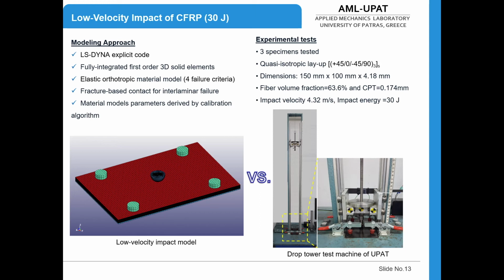And the idea is that we have this impact tower. We use this quasi-isotropic layup, plus 45, 0, minus 45, 90, symmetric. The dimensions of the impact sample are given here. And of course, the volume fraction is the typical volume fraction that we have already used. We use an impact velocity close to 4.3 meters per second, and an impact energy close to 30 joules.